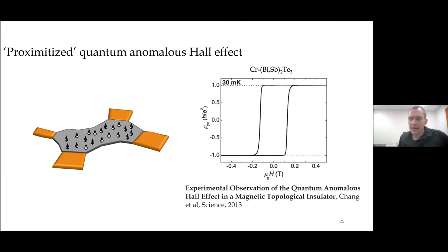So that is an approach with a lot of advantages, but it also has some limitations. And I think the one that people were most aware of at the time was the fact that the magnetic dopants that were realizing magnetism in these systems are not ordered, right? They represent a very strong disorder potential off of which electrons can scatter, and they can reduce the activation gap for electrons in these states.